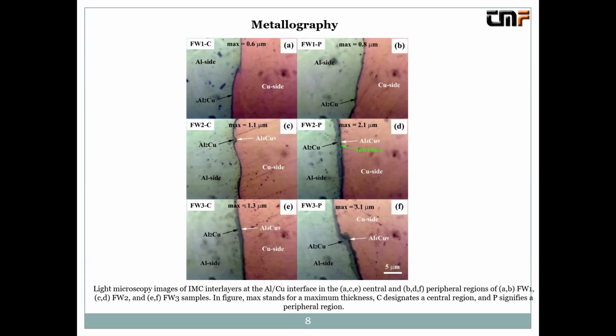So with increase of friction time, we obtained a continuous AlxCuy intermetallic layer, but an Al4Cu9 intermetallic layer starts to form, and the Al4Cu9 layer is now discontinuous. All those discontinuities in the intermetallic layer weaken the welded joint. Finally, for the longest times, we obtain continuous Al4Cu9 and Al2Cu intermetallic layers, but also there is formation of an AlxCuy layer, which we'll present a little bit later.